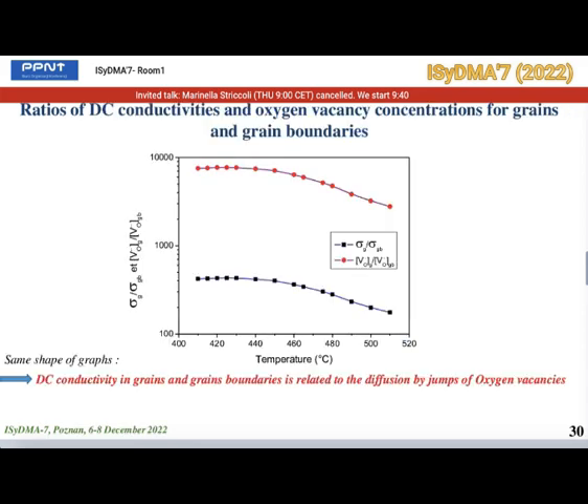And if we represent on the same graph the evolutions of the ratio of DC conductivities of grains and grain boundaries, and the ratio of oxygen vacancies concentrations, we notice to a first approximation that the two curves look the same. This allows us to say that at these temperatures, continuous conductivity in the ceramic grains and grain boundaries is essentially due to the diffusion by jumps of oxygen vacancies.